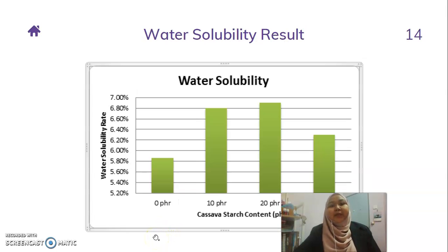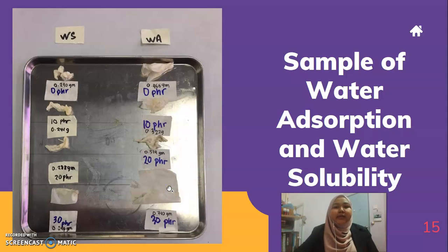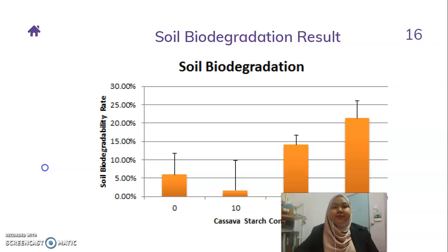Then this is the water solubility result. The highest water solubility is at 20 phr, where the film dissolves in the distilled water, and the lowest is at 0 phr. This is the sample of water absorption and water solubility. You can see a very fine thin film obtained at 30 phr, and for the others, the film accumulates and it is hard to form a thin film.